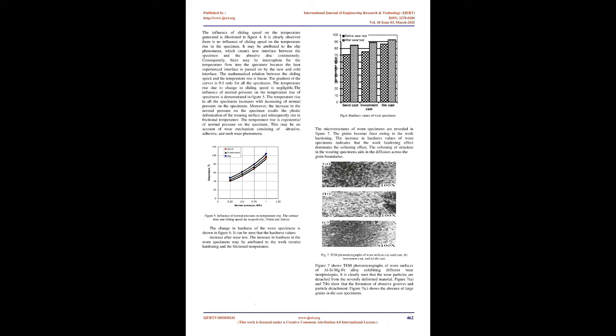Effect of contact time, sliding speed, and normal pressure on temperature. The influence of contact time on the temperature generated in the specimen is shown in Figure 3. The temperature rise in the specimen is proportional to its contact time with the abrasive disc during the wear test. With the increase of contact time, the corresponding frictional temperature rises steadily due to the increased conversion of frictional energy into heat energy. The influence of sliding speed on the temperature generated is illustrated in Figure 4.